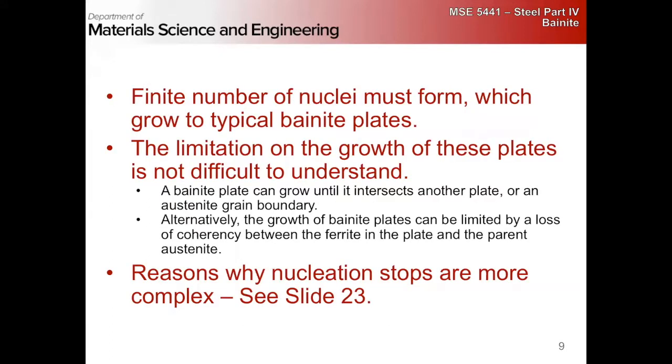So we have a finite number of nuclei that have to grow. They have to grow to bainite plates. Okay, so if we're in between the bainite start and the bainite finish temperature, we're not going to go completely. Both nucleation and growth have to terminate.